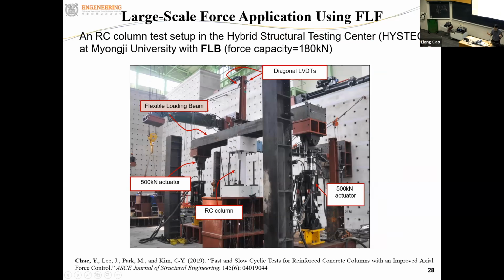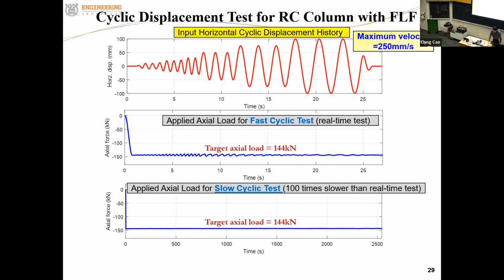Basically, we pull down the loading beam at the end, and we control the bending deformation of this loading beam using these actuators, which is proportional to the actual force applied to the column in the middle. So we conducted slow and fast, or real-time, cyclic loading tests for this given displacement loading history. We gradually increase the lateral displacement of this test setup.